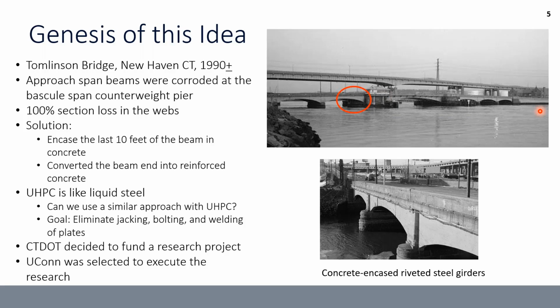Well, then UHPC has come along, which I call liquid steel. Very high strength material with tensile capacity as well as compression capacity. And the idea we had was maybe we can use UHPC to do a similar but much simpler approach to repair steel beam ends that are corroded. Again, our goal was to eliminate jacking, cutting, welding, and bolting of beam ends, to simply go in and pour some UHPC to repair and restore the shear capacity of the beam.